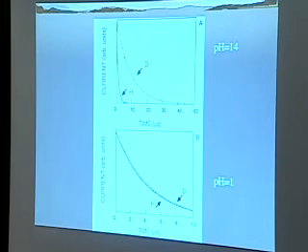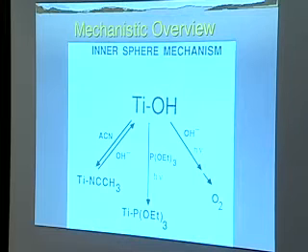So that argues that there must be a proton transfer in a critical step in this mechanism when we are in base, when we're oxidizing hydroxide, but not when we're in water. I was going to guess, actually, by the way, that it was going to go the other way around, because, of course, in the water, this is in acid, we're putting an extra proton or deuteron onto that water. It's really H3O+ that we're dealing with. So I thought if there was going to be a proton effect, it would be here, not over here. But clearly, there's a proton transfer in the hydroxide case. That is the key thing.